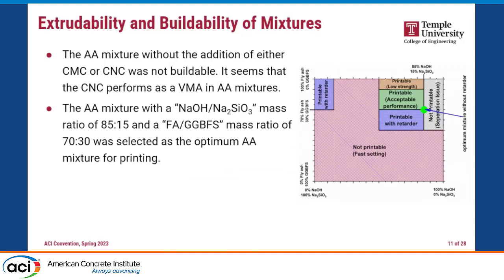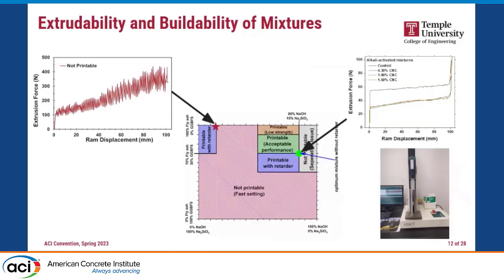Here's how we developed the alkali activated mix design. You see the combination of the activator as well as the change in the composition of the binder. We looked at which portion is printable, which portion is printable with retarder, and where's the optimum mix. You can see that here. If we look at this by the pressure graphs, you see the non-printable system at the left side, right? This has a very high pressure requirement, and you have a hard time to extrude it through. And at the right side, these are the optimal mixes I mentioned.